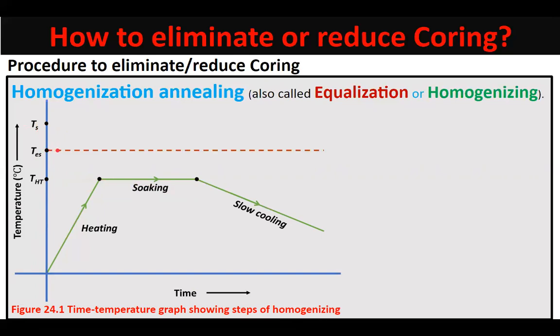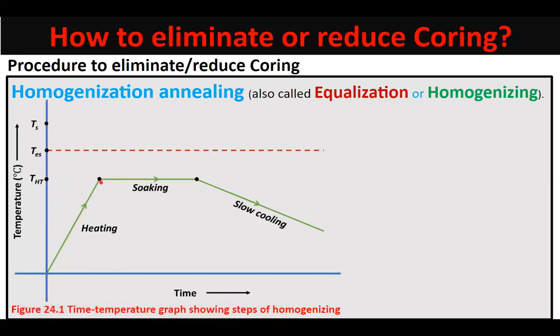So when we cool that alloy, we must note down this temperature. At this temperature, the casting would have actually solidified completely. When we reheat the casting, we should remain sufficiently below it, and sufficiently at a high temperature where diffusion can take place. So this heat treatment temperature has to be very judiciously selected: high enough to cause diffusion, low enough to be away from this TES, right?